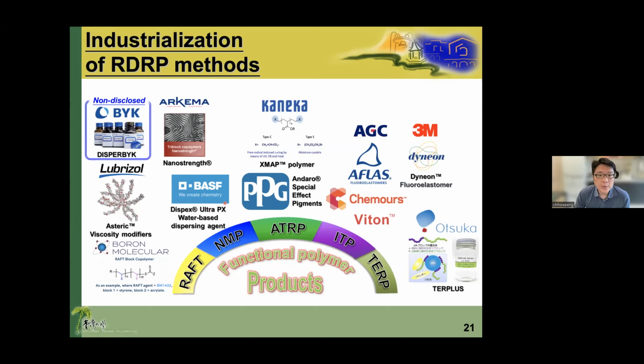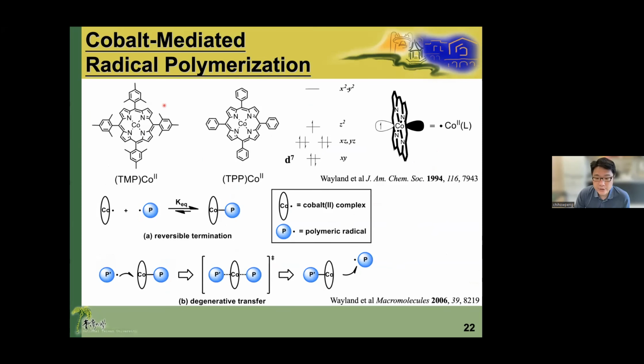So the cobalt-mediated radical polymerization was first developed by my PhD advisor, Dr. Wayland, using cobalt porphyrin complexes. Cobalt porphyrin complexes have the d7 low spin electron configuration, so the single electron is located on the dz2 orbital, making the whole complex like a metalloradical. So in the radical polymerization, it can deactivate radical to form the dormant species, and because of the empty site, it also can mediate the radical polymerization by the chain transfer process.